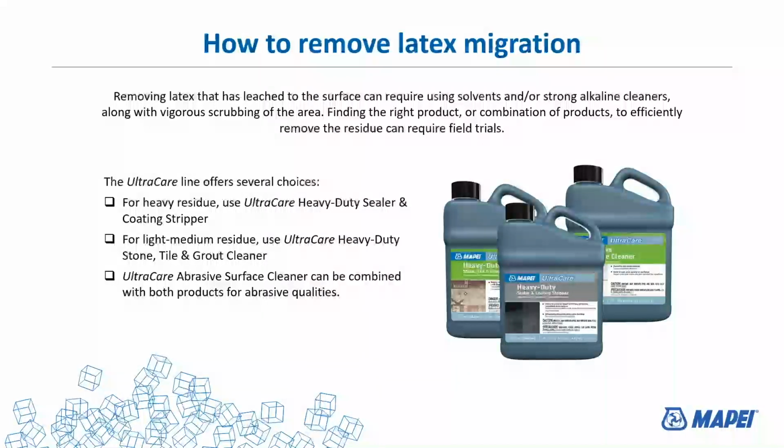The abrasive surface cleaner can also be used by itself or in conjunction with the heavy duty cleaner. It works quite well. You would apply the cleaner first, let it sit for 5 minutes, and then apply an equal amount of abrasive cleaner on top and hit it with a scrub pad. The abrasive cleaner doesn't need to sit. It works by abrasion. I would not mix the two together in a bucket and then use it.